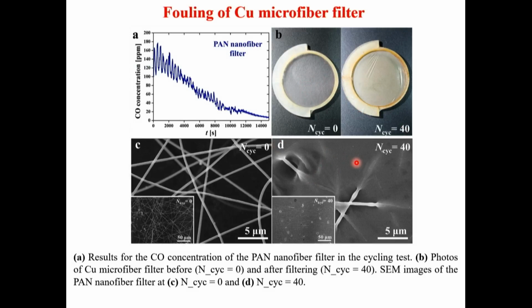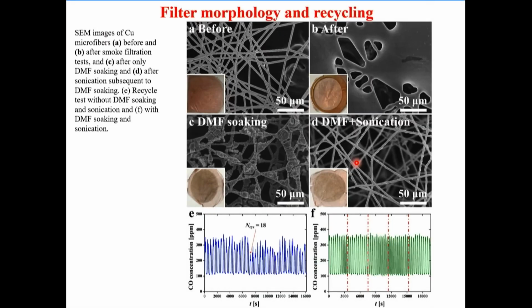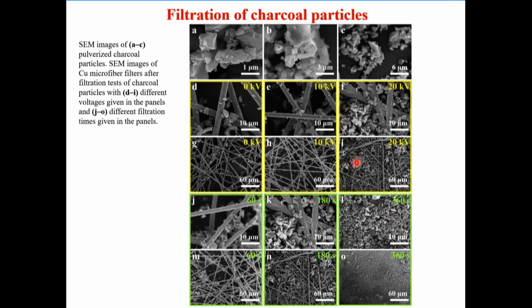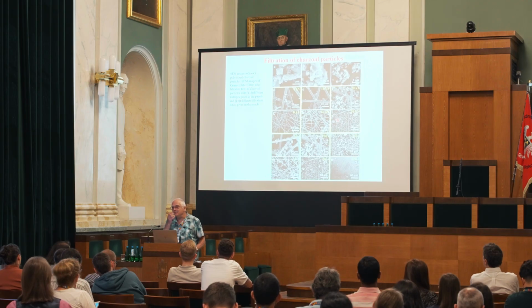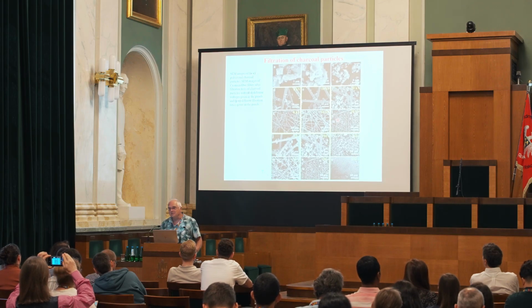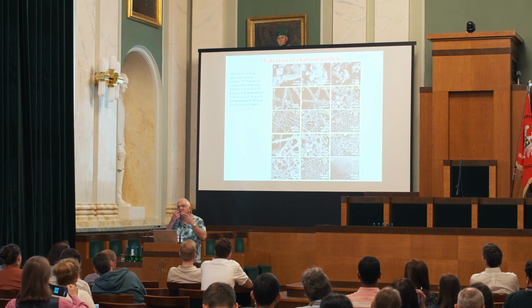It looks like a liquid film appears, but essentially it's not a liquid film. It's deposited soot. We demonstrated this type of interception with multiple particulates. I'm just skipping over all this. These are examples of different particulates we removed, and we showed also that we can clean these fibers very easily. In addition, the last thing I'll tell you is that when you have metallized fibers, you can also use them as an incinerator. You use joule heating from a battery of only 3 volts to effectively burn, for example, viruses which are intercepted.